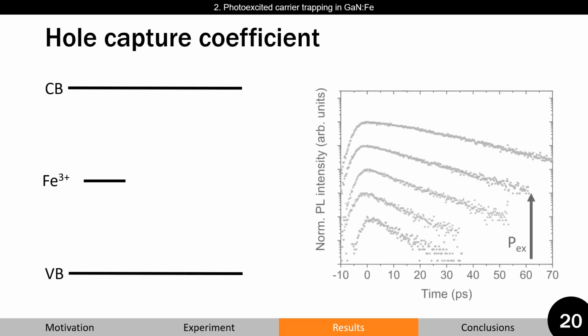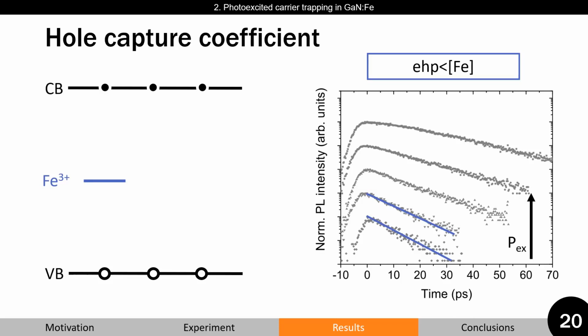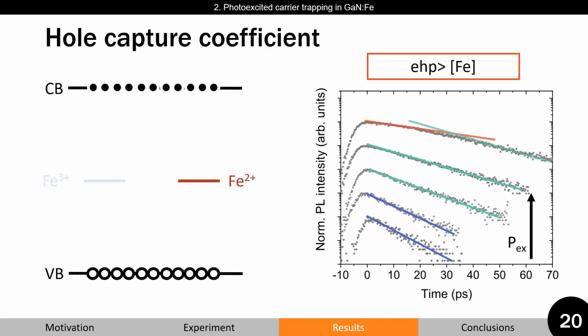We conducted excitation-dependent measurements. In other words, excitation is proportional to electron-hole pair density. For low excitation densities, when electron-hole pair density is much lower than the iron concentration, we see excitation-independent lifetimes, which can be attributed to electron trapping through the iron 3+ state. Under the highest excitation conditions, when electron-hole pair concentration exceeds that of iron, initially after the laser pulse, the iron 3+ state captures electrons, and the dominant capture process becomes iron 2+. Thus, we see this double slope exponential shape emerging.